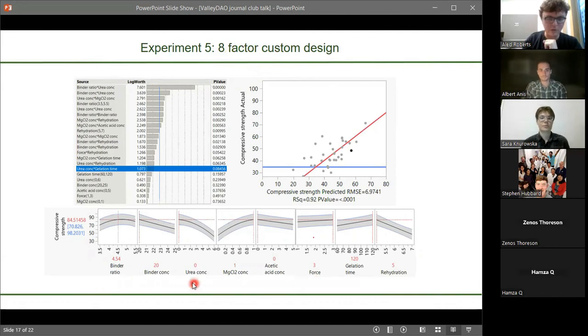Interestingly, it showed us that a lot of the additives that looked like they were initially going to be useful actually weren't. Adding urea after optimization actually didn't help. Same with acetic acid. The materials were stronger with 0 acetic acid. And interestingly, adding magnesium chloride did help, even though in the initial additive screening experiment it didn't help because we just overloaded it, but we carried on looking at it out of curiosity. But yeah, it gives us very high quality information about the system.